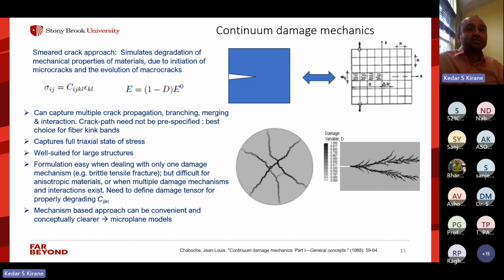One of the main reasons is that the direction of the kink band is not known a priori. So it has to be a prediction from the model. And so this approach is most relevant to this kink band failure. So what essentially happens in this approach is that we introduce a state variable called damage variable D. When D is 0, it implies that the material is undamaged, and it slowly evolves to a value of 1 when the material is fully damaged. And the failure is kind of smeared. So if this is a crack, it is represented by a band of smeared damage. And in this band, D will go from 0 to 1. And when it goes to 1, its stiffness is lost. So essentially, the formation of a crack is likened to the loss of stiffness of that material. So it's smeared in a region whose stiffness is lost.